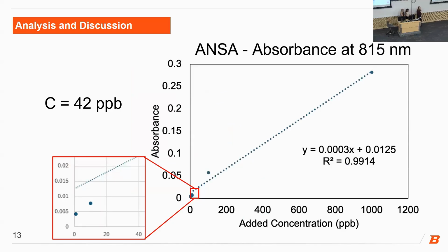Okay, so we used the data from our ANSA reductions and we plotted the instrument response versus the concentration of the added standards. And then we generated a trend line of this plot, and then we calculated the x-intercept to that trend line. From the x-intercept, we determined that the concentration of our unknown was measured at 42 parts per billion. While this is still in the same order of magnitude, it's still a factor of 4 off of what we expected at 10 parts per billion.